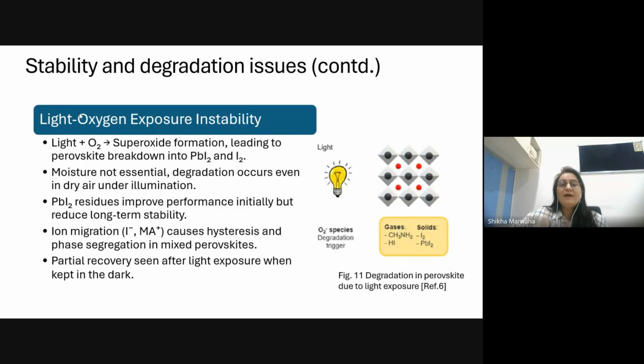Another is light and oxygen exposure instability. Once the material is exposed to light, degradation happens. When there is an excess of light, there is a formation of superoxides. Because of that, the methyl ammonium lead iodide is broken into lead iodide, and it is also broken into iodine gas.